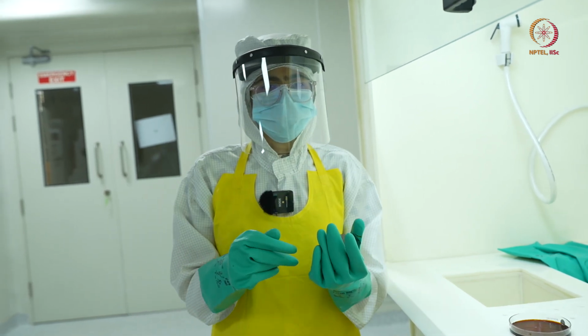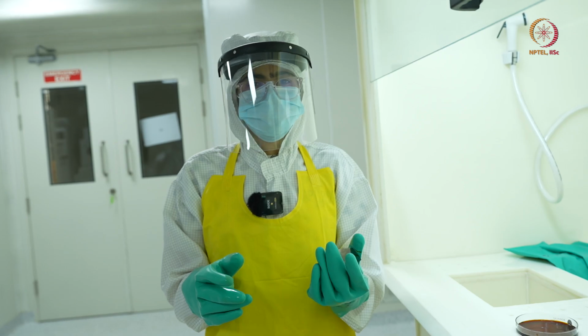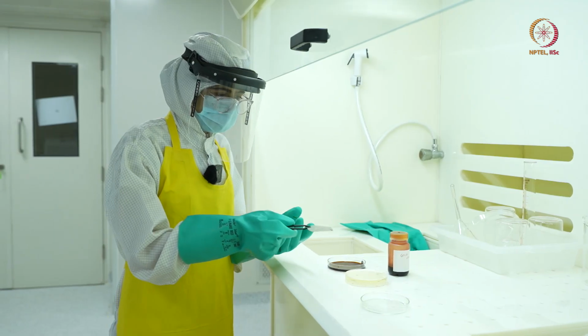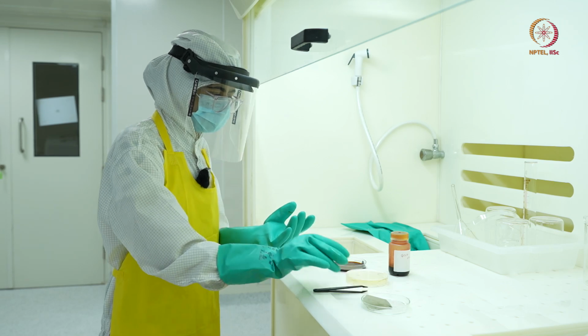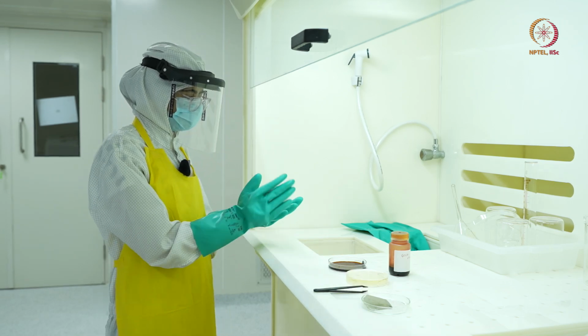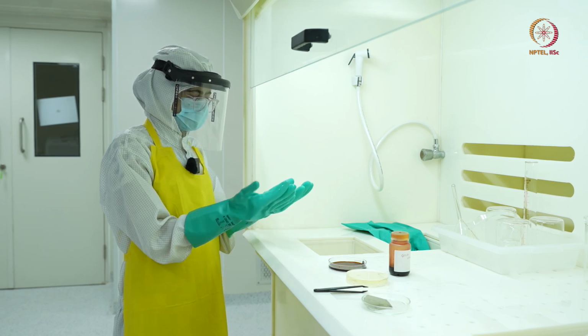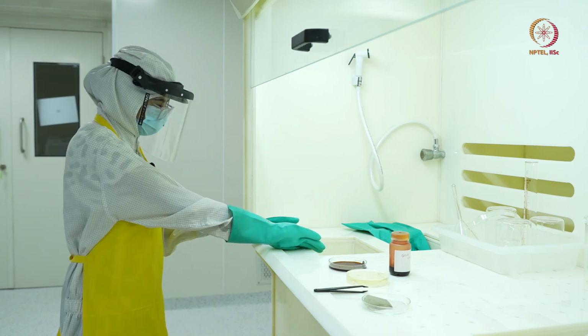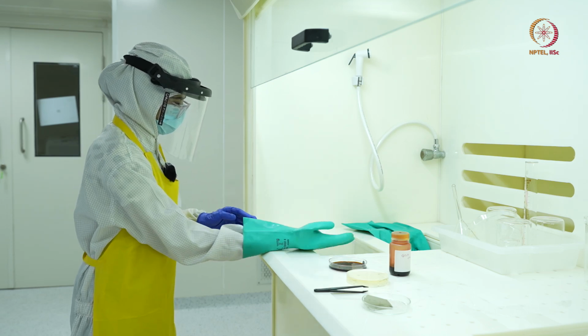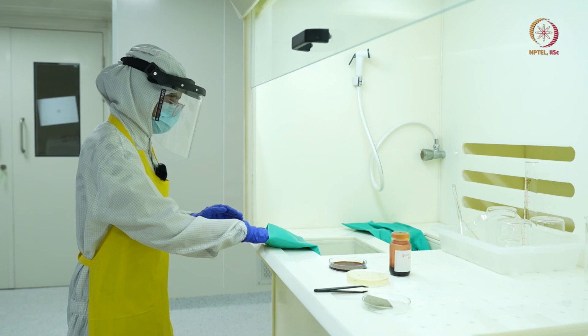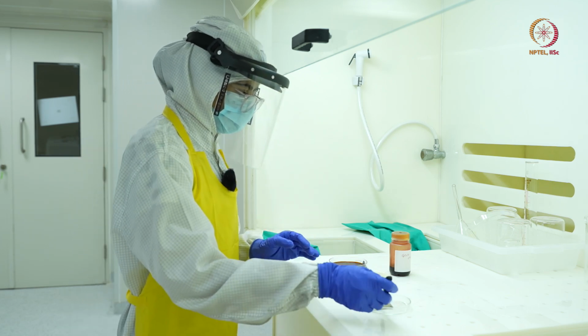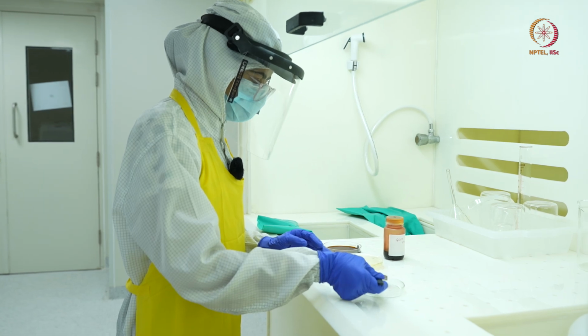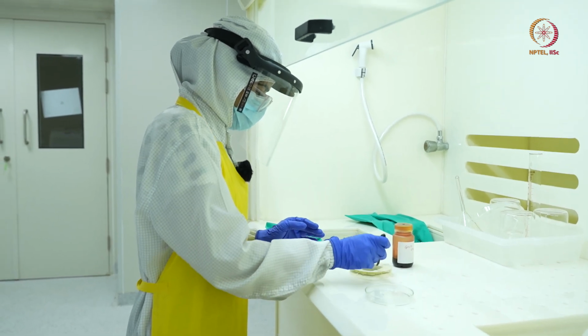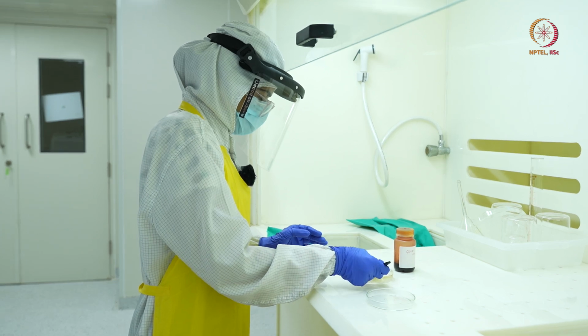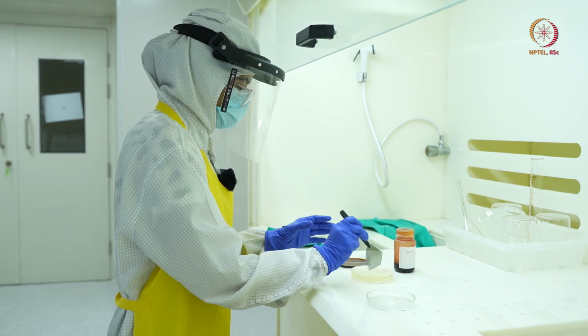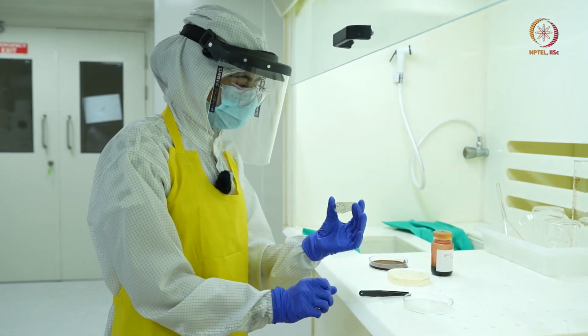So I'll go to the nitrogen gun and we'll have a closer look at the nitrogen gun as well. Now before touching any other thing, I should remove my contaminated gloves, and I should not touch the contaminated part. So I'll carefully remove my gloves and I'm ensuring that I'm not touching any contaminated part. And again, this can go for one more DI water rinse before I put it for blow dry. So I have taken the sample out of my DI water and we'll give it a blow dry.